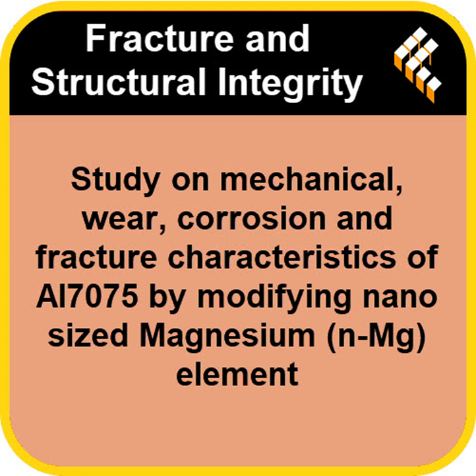It's a classic case of overkill. You get something called grain coarsening. At these excessive concentrations, too many of those Mg-rich intermetallic phases form, and the Al3Mg2 particles essentially start clumping together. Ah, so they stop being efficient. Exactly. Instead of many tiny efficient obstacles, you end up with fewer, larger, inefficient roadblocks. This actually reduces the alloy's ability to resist movement and deformation. And the visual fracture analysis backed this up.